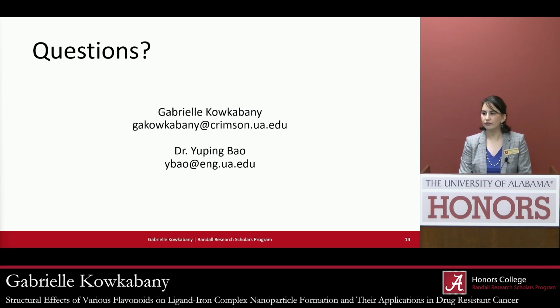So I'm curious if there is a particular nanoparticle size that you are trying to achieve, and if so, about what size are you looking for and why specifically that size? That's an interesting question. The short answer is no, we're not actually looking for a specific nanoparticle size. When we do this synthesis process, we generally study the ratio effects, and so we use ratios of ligand to iron from 1 to 5 all the way to 5 to 1, and then we look at TEM images of all of those nanoparticles to see what size has been created based on the amount of monomer that's available during nucleation and the formation of these nanoparticles. And then from there, we can see the ones that are most consistently formed.